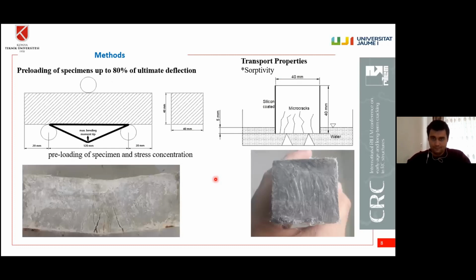For the self-healing evaluation and for the mechanical evaluation, we used the 3-point bending test. We used this test on purpose because we are trying to evaluate the potential of autogenous self-healing in the presence of binary use mineral admixtures. But since we use the specimens for the sorptivity test, it is not favorable to use a notch here. Therefore, we make the stress concentration high by using 3-point bending, as you see here. Even under 3-point bending, specimens normally undergo very abrupt and catastrophic failure. But even at 80% of the ultimate deflection, the specimens were able to resist the damage. As you can see, we get very ductile behavior.